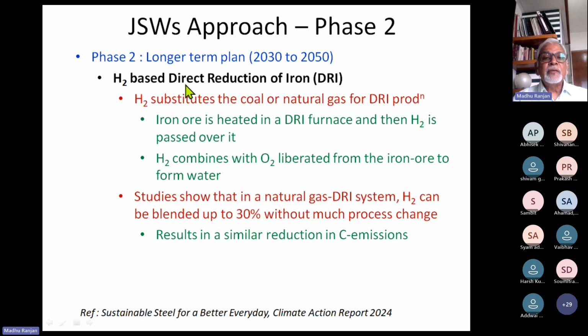So, hydrogen based DRI production. The alternative route of making iron is DRI, direct reduced iron. Here hydrogen substitutes the coal or natural gas for DRI production. So how do you do it? You first heat up the iron ore in a DRI furnace, and then hydrogen is passed over it. The hydrogen combines with oxygen and reduces the iron ore into iron. Studies show that in a natural gas DRI system, hydrogen can be blended up to 30% without much process change. So this will have a similar reduction in carbon emissions.